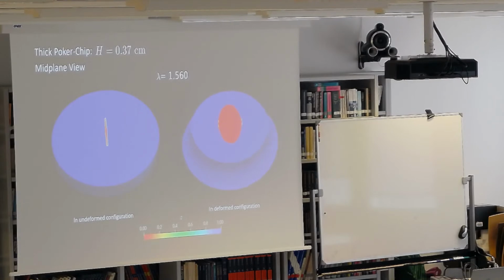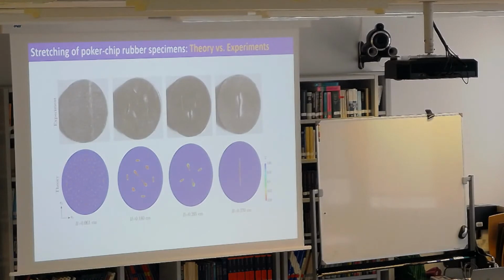This is actually very interesting. When you pull on a thick specimen, the crack nucleates near one of the boundaries, and it propagates downward. So you're pulling in this direction. The crack goes down, which is counterintuitive. The reason why it goes down is because of incompressibility, right? And again, Griffith says that happens, and then you compare what happens in the midsection, and okay. This, to me, looks very convincing. So I think this is very encouraging.